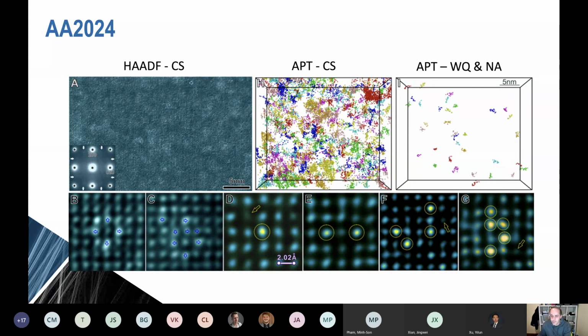This is from 2024. And this sample here is showing clusters that have formed in the cyclically strengthened material. And the one on the right are the clusters that have formed in the head of exactly the same sample. So we have a sample where we apply the cyclic vibrations, the cyclic plasticity, uniaxially in a fatigue machine. And so this collection comes from the gauge and this collection comes from the head. And it's quite important to do that direct comparison because then both samples have identical thermal histories. And you can see there's an enormous difference in the density of clusters that have formed.